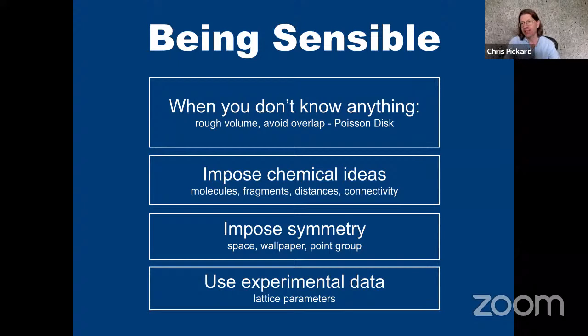It's probably not a good idea when you're building your random structures to have the atoms on top of each other. So you could have hard sphere repulsion around each of those atoms. And that leads to something like a Poisson disk distribution of randomly distributed atoms. That's basically what I mean: it's probably as random as you could get. We know the rough volume, so we don't choose a completely random volume. We have to set it to be roughly the right volume.